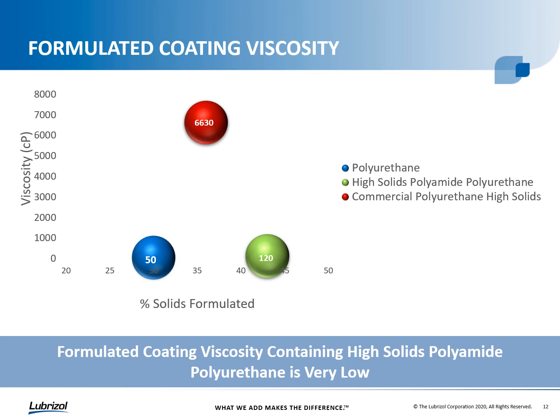And in this chart here, we're looking at formulated resin viscosity. So these would be formulated clear coatings made from the various resins. And then we're also comparing against a commercial high solids benchmark product that we bought off the shelf at a big box retailer. So the blue bubble is your traditional lower solids polyurethane coating formulated at around 30% solids, and you can see very low viscosity at 50 centipoise.